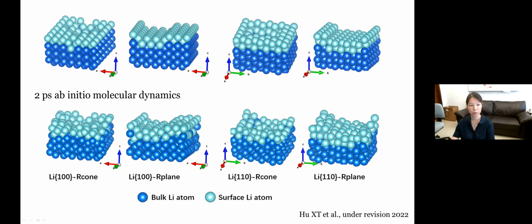And in the other model, we use the so-called plane model. We also remove half of the lithium surface atoms, but they're randomly removed, so the surface is rather flat. Then we look at the difference when relaxing these surfaces for the lithium 100 and lithium 110, after a 2 picosecond ab initio molecular dynamics. And this is what we show. We see that in terms of the plane model, for both the 100 and the 110 surface, they're actually very similar. So they remain kind of flat. But for the cone model, in the case of lithium 100, the cone remains here, although it might get a little bit shallower. But in the case of lithium 110, the cone is almost filled by the surface atoms of the lithium.